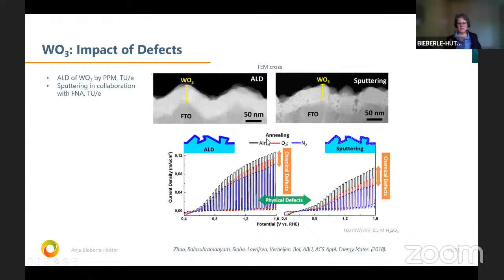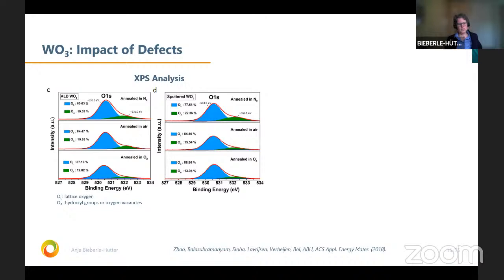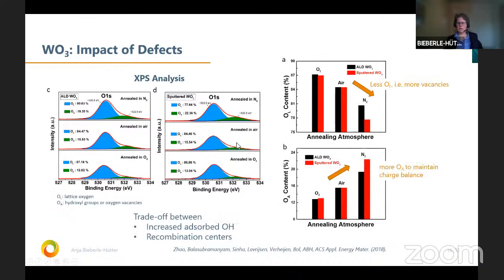And we did the same experiments for the ALD. And also when you think a bit regarding application-wise, it's for sure nice if you can just anneal in air and get a good performance. So here we show what is actually behind this. So we did XPS analysis, and you see here the lattice oxygen, the blue one, and the green one, the adsorbed oxygen, which is usually attributed to hydroxyl groups or to oxygen vacancies. And you see actually here a change as a function of the annealing, and we summarize it here.